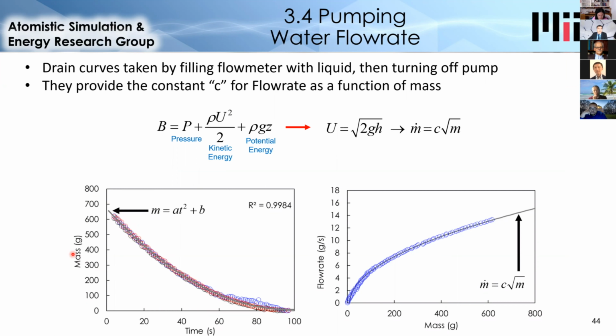But since I now have mass versus time, I can take the numerical derivative and get mass flow rate versus time. And with mass flow rate versus time and mass versus time, I can plot mass versus mass flow rate parametrized by time. And now this is the exact relationship I want, where I can read off mass. So if I have 400 gram mass in the pump, this tells me the flow rate is 10 grams per second, just based on conservation of mass and Bernoulli's equation. You can see that this experimental curve matches very well to the expected shape based on Bernoulli, where the mass flow rate is proportional to the square root of the mass.